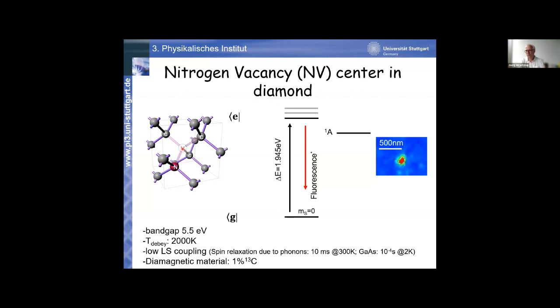So it's a rather straightforward way of making these defect centers, and it's very robust over a wide range of parameters like pressure, temperature, and so on and so forth. Physically, the spin state of this NV center is a spin triplet, so it's not S=1/2, but S=1, which means you have 3 magnetic spin sublevels.